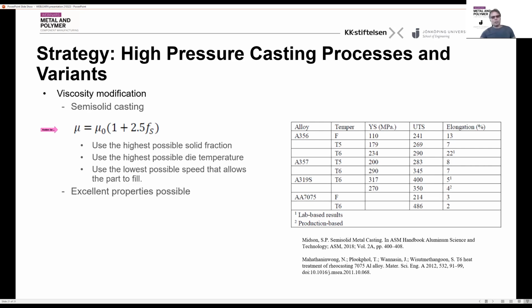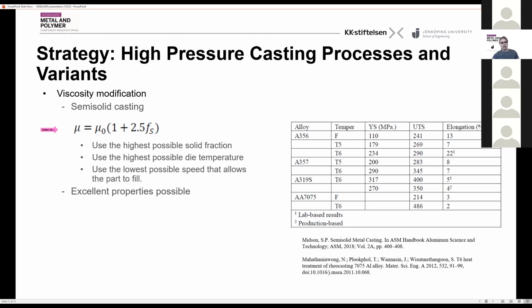And you can actually use this concept by understanding that if you have a certain portion of solid, you will increase your viscosity. And that means that if you abide by rules such as increasing the viscosity to the maximum that you can, which means using the highest possible solid fraction, we get the highest viscosity, which would be a turbulence reduction.